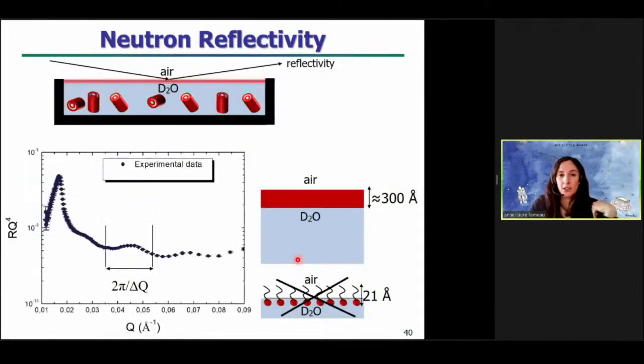To answer this question, we use neutron reflectivity experiments. In a neutron reflectivity experiment, the neutron beam is reflected at the air-D2O interface, and you just measure the reflectivity coefficient as a function of the distance to the surface. Here you can see the reflectivity curve obtained for the interface between air and the tube solution. On this reflectivity curve, you can clearly see the presence of smooth interference fringes.